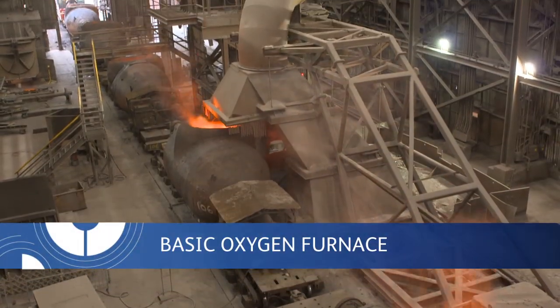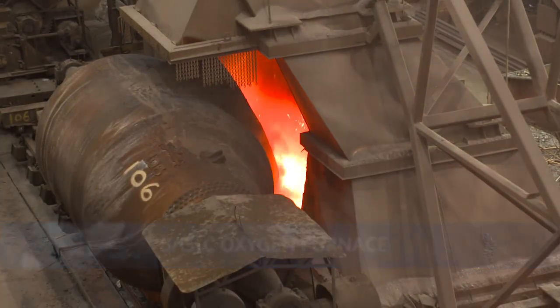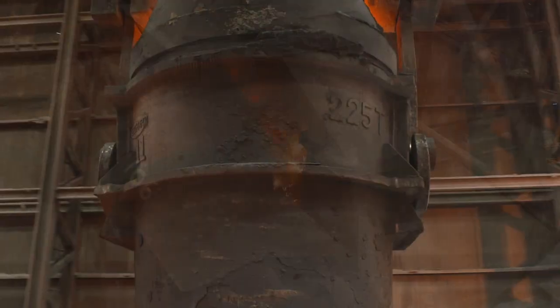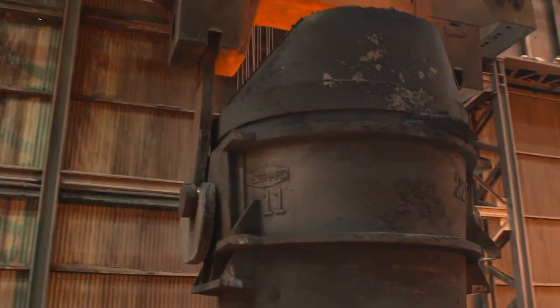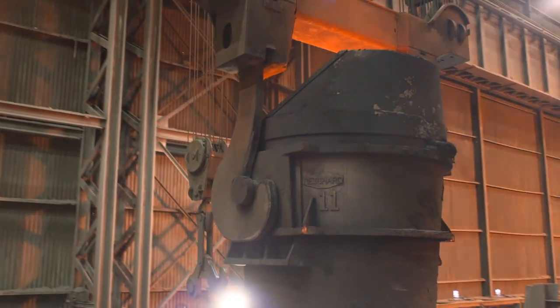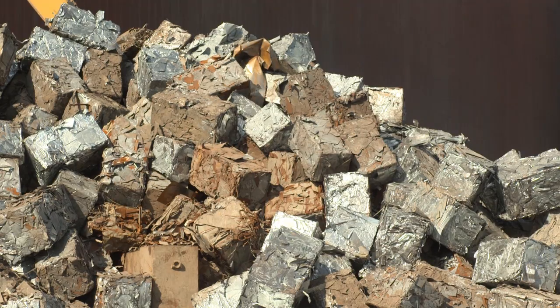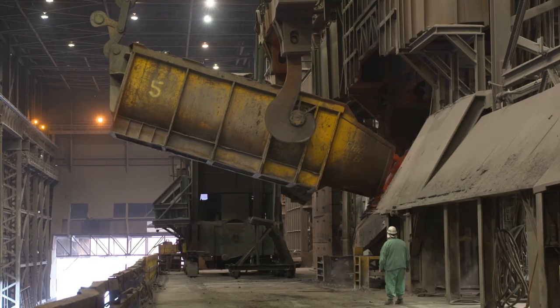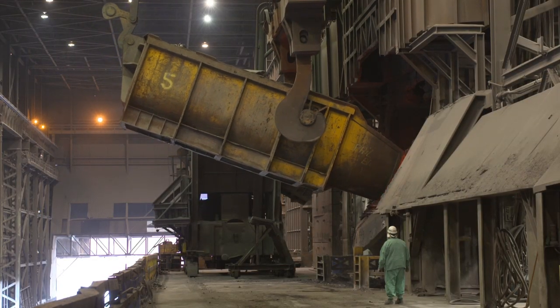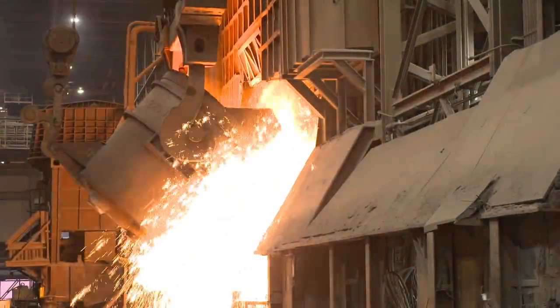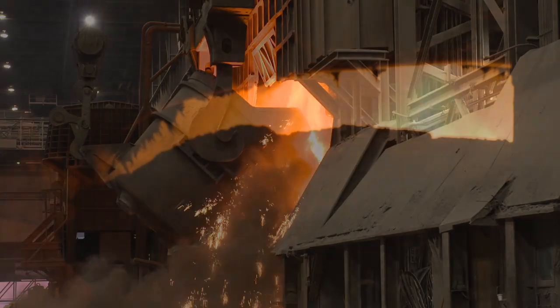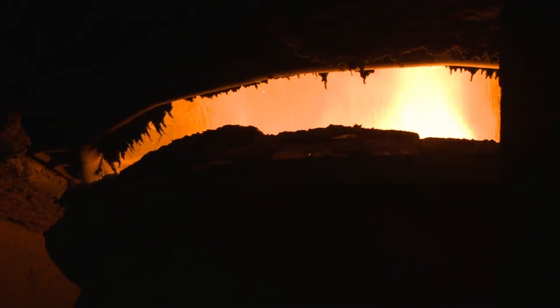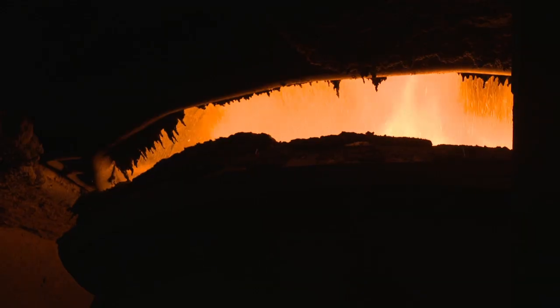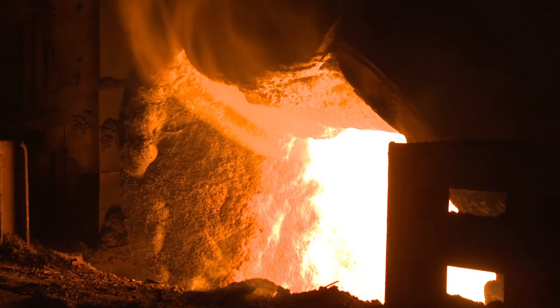At this point, the molten iron is not yet steel, so the contents of the bottle cars are poured into huge ladles and carefully transported by overhead crane to the basic oxygen furnace, or BOF, where the steel making begins. Before the molten iron is poured into the BOF, a load of scrap metal, a natural byproduct of the area's many automotive processing plants, is added for a mix of approximately 25% scrap and 75% molten iron. Pure oxygen is then blown into the mixture at more than 21,000 cubic feet per minute, removing the carbon, melting the scrap, and creating steel.